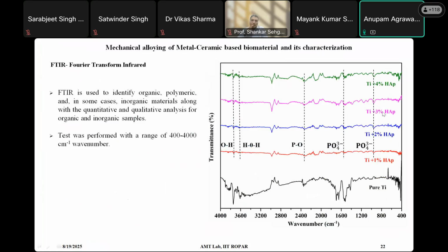So in different ratios, we mixed hydroxyapatite in the parent metal powder, that is titanium, and we wanted to see what is an ideal percentage to mix. Initially we tried with several percentages, and we kept the hydroxyapatite percentage low because we found at a later stage that as we keep on increasing the hydroxyapatite percentage higher, it becomes difficult for us to retain some of the functions.